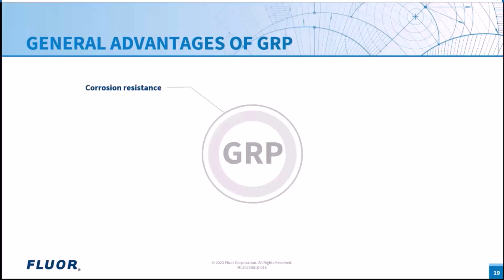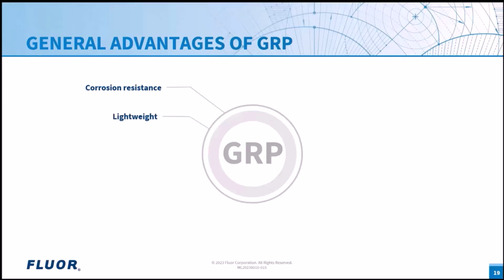Talking to GRP experts, there are several advantages of GRP. As GRP is chemical resistant by nature, it is a preferred choice in applications where internal corrosion is a major concern. This resistance extends to various chemicals and environmental factors, unlike, for example, HDPE, which is not resistant to hydrocarbons, and unlike steel, which can corrode and degrade over time and is sensitive to microbiologically induced corrosion, also known as MIC. GRP materials are significantly lighter than steel, resulting in reduced structural requirements for supports. Furthermore, GRP is a non-magnetic material, making it suitable for applications where magnetic interference is a concern, such as in the electronics and in the telecommunication industries.